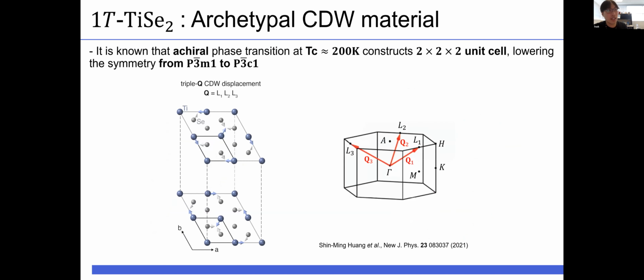Our material, 1T titanium diselenide, also has multi-Q charge density wave. It is known that it has a structural phase transition at 200 Kelvin, constructing a 2x2x2 unit cell, and the atoms move along the summation of three phonon eigenvectors at L points. The left figure shows this CDW displacement. I will keep talking about L points and M points. These mean the high symmetry zone boundary points in a primitive cell. The right figure shows the first Brillouin zone in reciprocal space. Here is the L point and here is the M point.